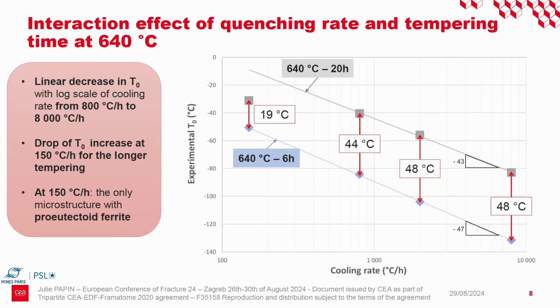One of the explanations of this drop is that the microstructure for the quench at 150 degrees per hour is the only one that still contains proeutectoid ferrite. And this quench is very slow, so it's more like a cooling than a quench. And there is a phenomenon of auto-tempering, and this may smooth the effect of the tempering after.